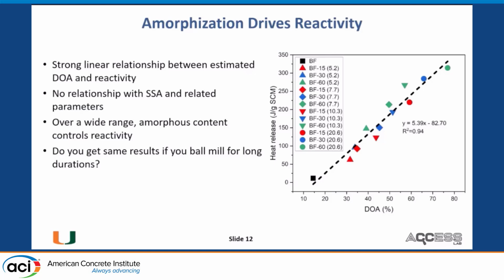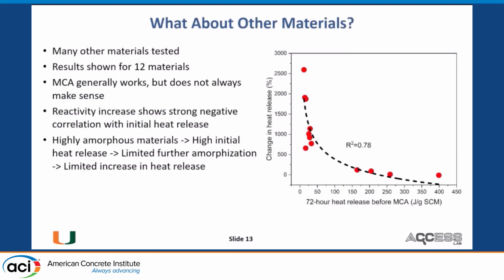So we conclude from this, at least preliminarily speaking, that over a wide range of amorphous content, the amorphization controls reactivity. What I don't know here is a planetary ball mill is a very specialized piece of equipment. I don't know if you just take a standard ball mill and grind for a very long period of time, if you would get similar results. There are a number of other different mills and milling configurations, etc., that we haven't explored, although others have.